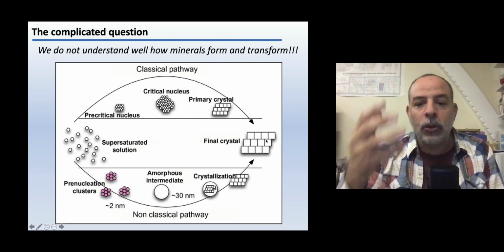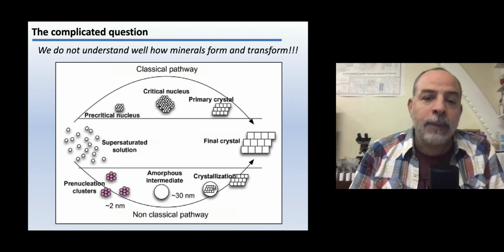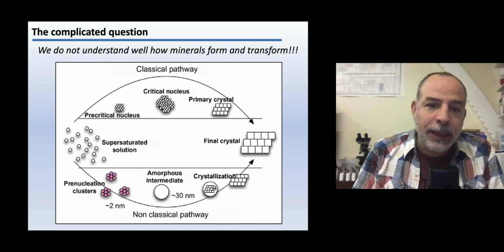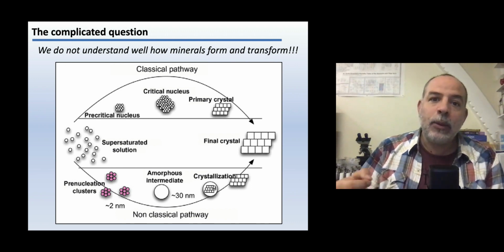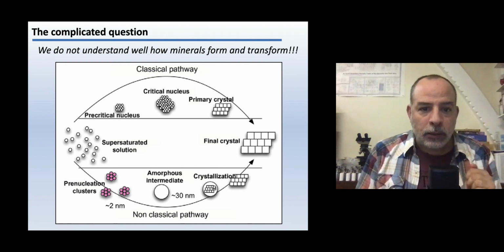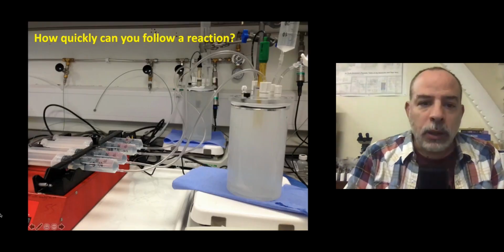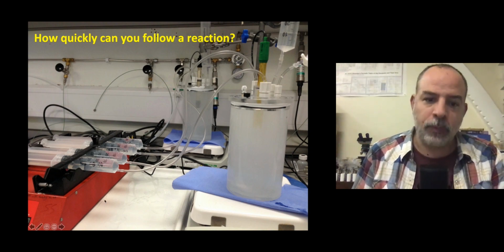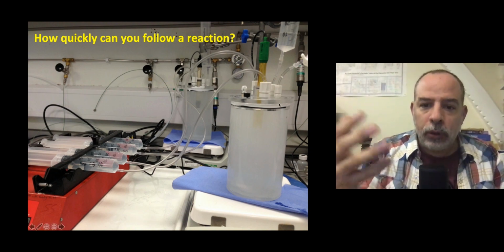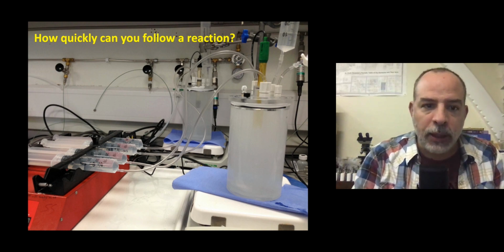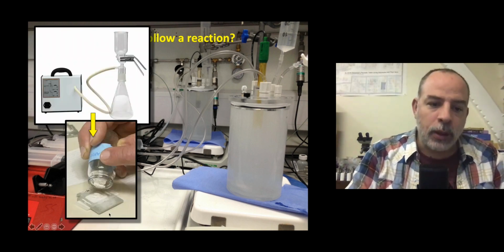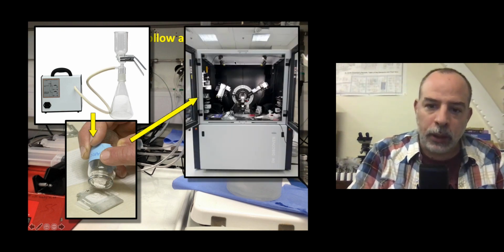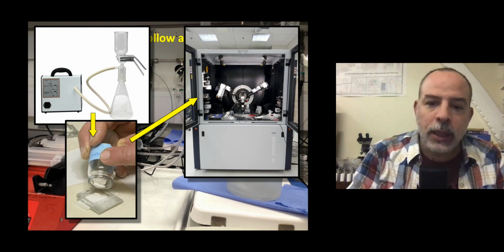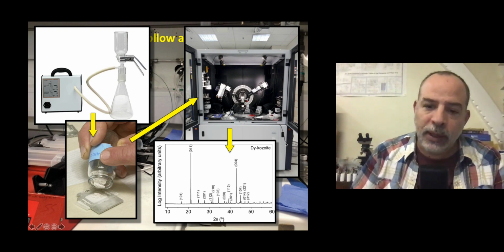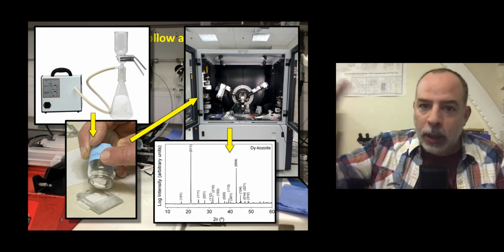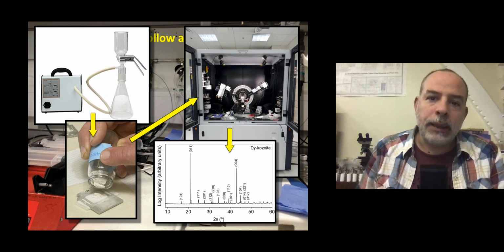The problem is that these branches, although this looks very simplistic in this diagram here, are processes which are extremely fast. They can take place in seconds, tens of seconds, and they are very difficult to follow using conventional techniques. So synchrotron radiation, synchrotron-based techniques are very useful for this purpose. So imagine that you are doing an experiment like this in which you are crystallizing a solid from solution, okay, by mixing solutions. So how do you follow the reactions here? You need to take your solids from the solution, and you can do this by using vacuum filtration, and then you have your powder, you put your powder on a holder, you put this holder with the powder in a powder X-ray diffraction instrument, and from here you can obtain structural information. You can identify your phase or phases and do quantification if needed. Okay? And then you can go, for example, to the scanning electron microscope to do particle size distribution analysis.